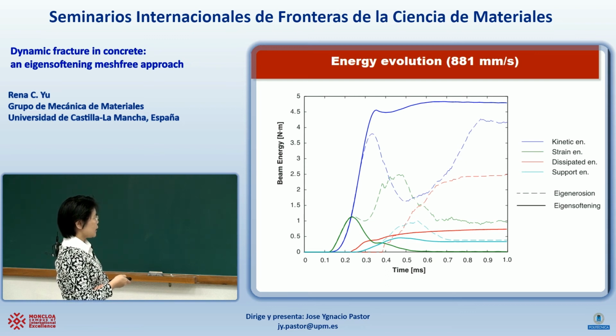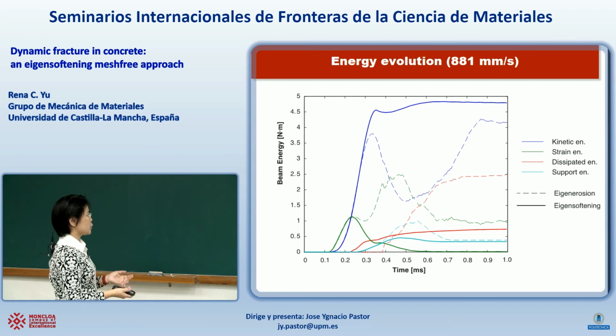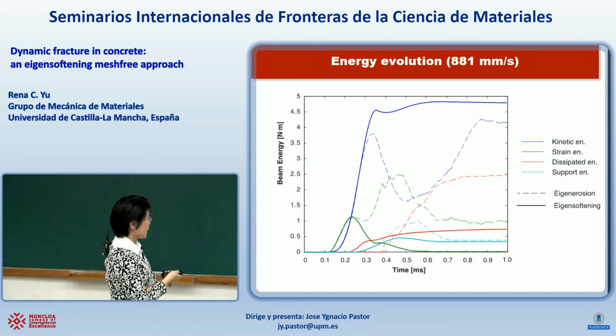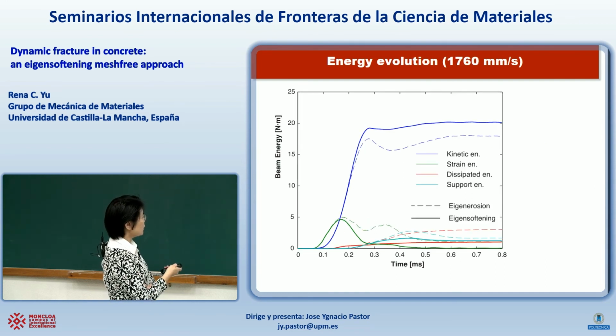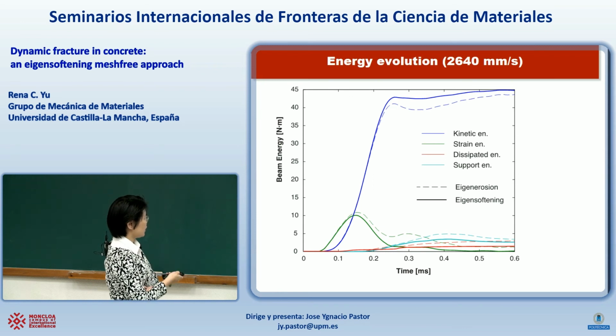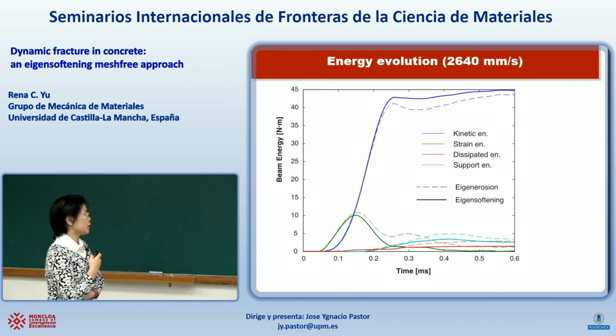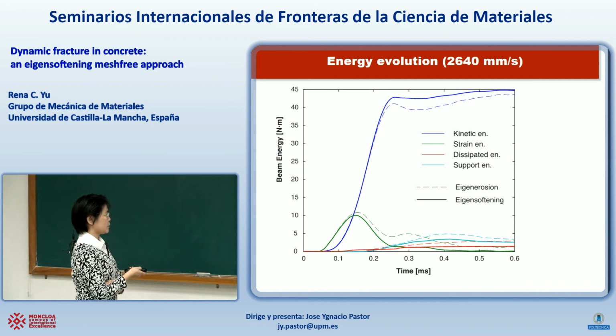I have to say that the work done by the support, for which we also use the contact algorithm to model the support, is quite significant compared to the dissipated energy. Actually, if we see the following velocity, they are almost of the same order. And this is the following one, the maximum velocity. So this is the dissipated energy. This one is the support energy, actually higher. So it is very important to take into account the work done in the support.